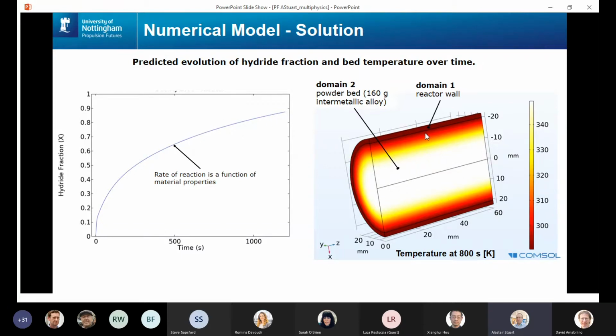What's happening in the container? Well, there's a temperature difference in the container. I've given you a plot of that, and you can see through this temperature scale that it's hottest in the middle. Then as we get towards the walls of the container, it's reaching the cooling temperature, which I think was about 20 degrees, about 290 Kelvin. The solver is then revealing to me in this application how the material will perform. I've not had to make the material, I've not had to build a prototype, but so long as my inputs have been correct and I've used the physics correctly, I have some idea of the potential of this material for this application.